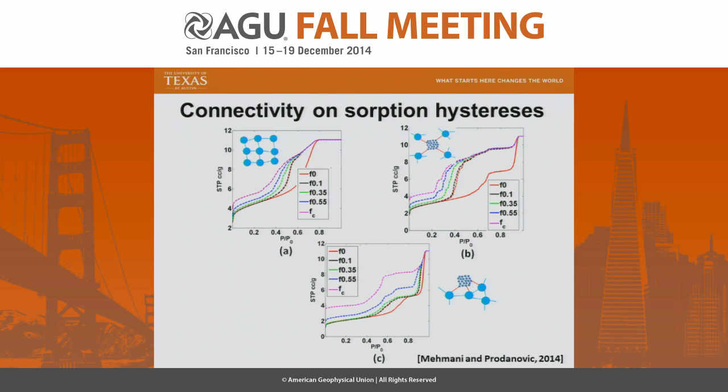And we said, well, okay, we will use our network models and just simulate natural sorption hysteresis and see how they look. So for single scale, it looks like a type 1 and type 2 hysteresis. That's fine. The second network type, where the smaller scale cluster of pores is acting in series with respect to its adjacent larger scale pores, we see a type 3 hysteresis. And that's pretty cool, because the classical understanding is that if I have slit-shaped pores, then I will have a type 3 hysteresis. Here we just use spherical pores, and it's actually the topology that is mimicking this behavior.